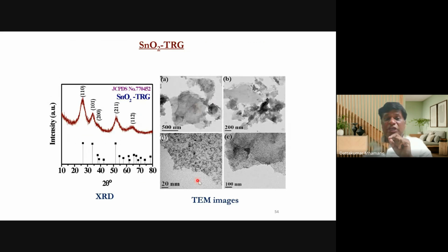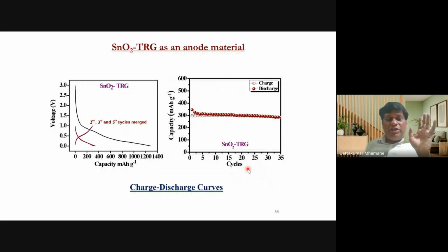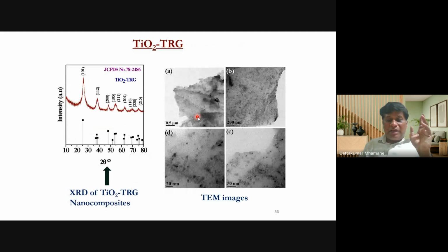So this is the tin oxide. You can see tin oxide particles are very, very tiny, around 1 or 2 nanometers. And you can see that all the particles are present on the graphene layer, by the same method. We confirmed with X-ray diffraction, many things we confirmed, and we measured its capacity, and see it is very stable up to 35 cycles, and we got around 300 milliampere hour per gram capacity. And then this is TiO2 graphene.